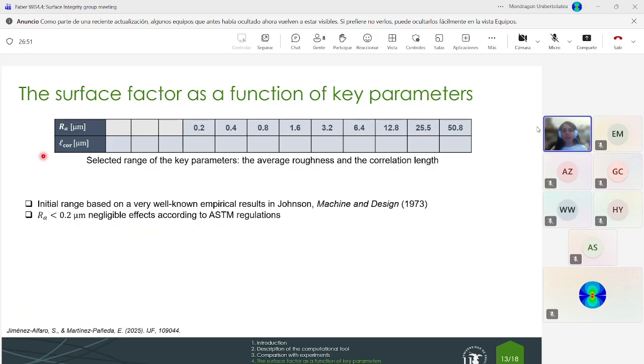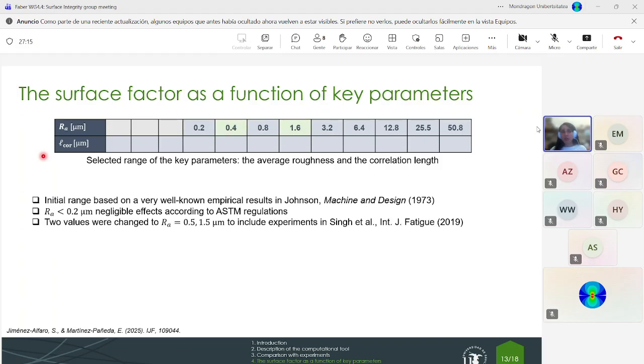And then we have reduced this range on the lowest side, because for average surface roughness lower than 0.2 micrometers, according to the ASTM regulations, the effect in fatigue is negligible. So we have just checked that this is fulfilled for 0.2, and we have not analyzed the other cases. We have also changed two values, to include the fact that in the experimental campaign by Singh et al., the average surface roughness was 0.5 and 1.5 micrometers. So we have just changed these two.